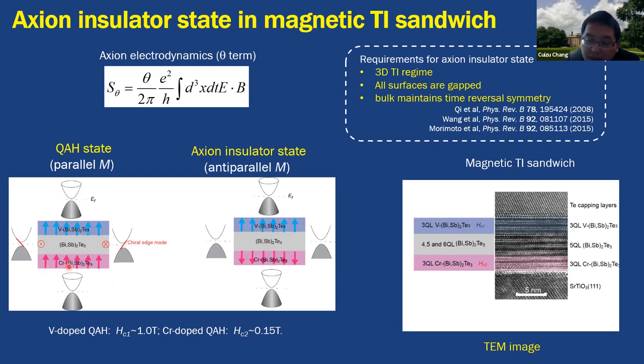This is vanadium doped bismuth antimony telluride on top, in the middle is undoped TI, and on the bottom we glue the chromium doped bismuth antimony telluride. Because the top layer and the bottom layer have different coercive fields, in principle, at some magnetic field regime, we could realize this kind of anti-parallel alignment. The top surface points up and the bottom surface points down.